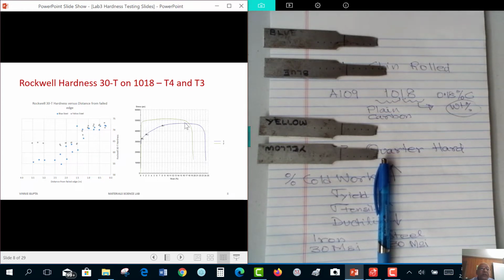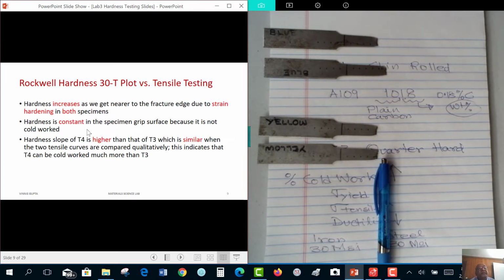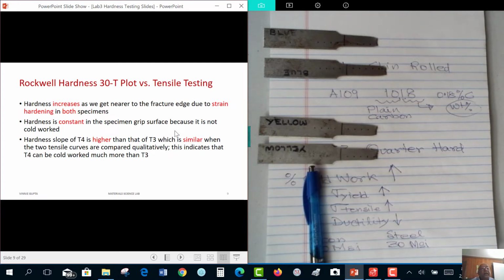And you can see that the slope of this curve, which tells us about its ability to cold work, in blue is higher than here, which is expressed by that strength ratio. So again, we see a higher slope. The hardness increases faster in blue than it does in yellow steel. So hardness increases as we get nearer to the fracture edge due to strain hardening in both specimens. Hardness is constant in the grip surface area because it has not deformed at all. And the slope of T4 is higher than T3, which is what we found from strength ratios.